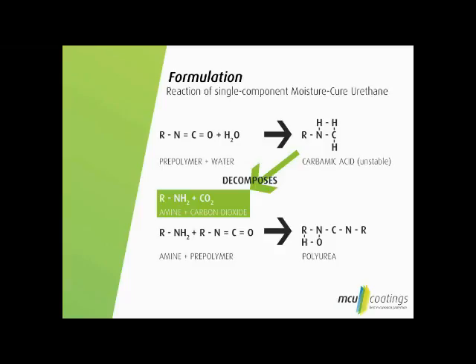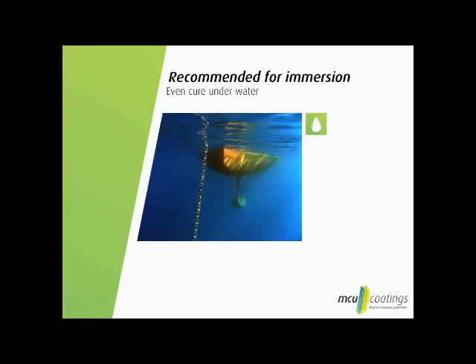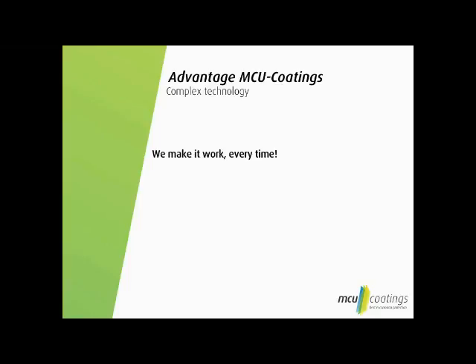These reacted polyurethanes, or more correctly, polyureas, are extremely different from two-component urethanes. These coatings perform perfectly in immersion and even cure underwater. Two-component urethanes are not recommended for immersion, and in fact cannot cure in the presence of water or high humidity. This technology is very complex and can be more troublesome to manufacture than epoxy or two-part polyurethanes. MCU Coatings is dedicated entirely to moisture cure coatings. We make it work every time.